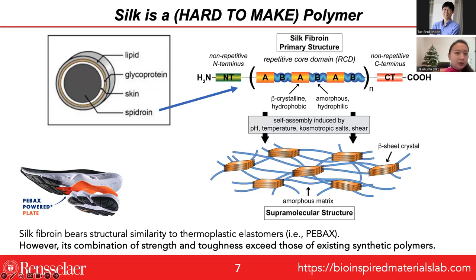And so when the organism creates this protein, it is disordered and unfolded. And during the spinning process, a variety of things happen. pH drops, cosmotropic salts are introduced. There's the shearing and elongational flow. And this protein is able to assemble into this semi-crystalline material where you have these little nanocrystalline domains of the A block that hold the material together, give it the stiffness and the strength and the elasticity. And then you have the B block, which serves as an amorphous matrix that gives it its toughness, its energy dampening properties.